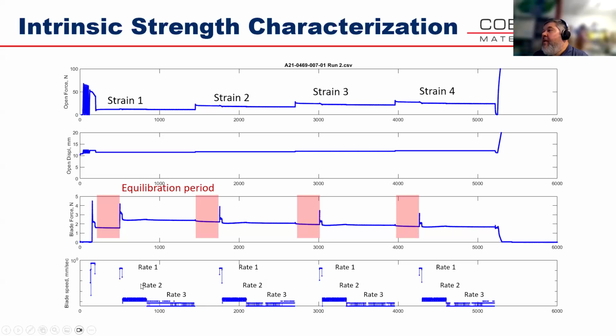But then for the second step, we repeat the procedure, and the third step and the fourth step, it's the same procedure. We start with a fast cutting rate, and then slow down by a factor of 100, and then slow down by a factor of 10. And that's the procedure that we're using to build up the data set that we need to measure T naught.